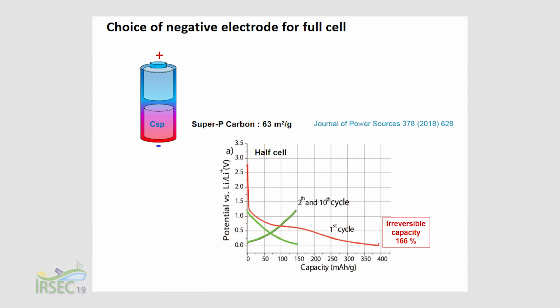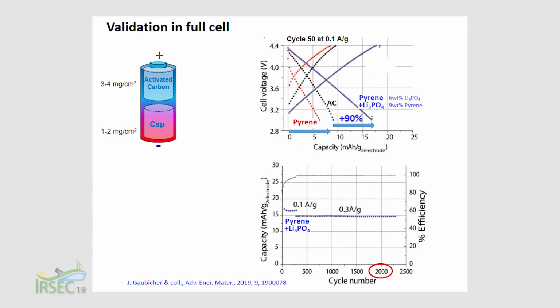So we have made full cells. For the full cells, we have used carbon Super P. I need to say, this is a very good model electrode because it has a huge irreversible capacity at first cycle, almost 200%. So we will see how efficient our system for pre-lithiation is. So the full cells have activated carbon in the positive electrode with or without the two additives, and carbon Super P in the negative. So here is at cycle 50.